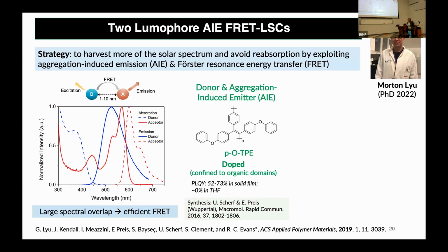So in this case, we use two new lumiphores now that we haven't seen yet. So our donor is this polymer here. It's actually an aggregation-induced emitter. So this donor polymer is not emissive when it's not aggregated. So in a good solvent, the quantum yield's around 0%. But when it aggregates, you switch on the luminescence. And so in a thin film situation, you can get quantum yields up to 70%.